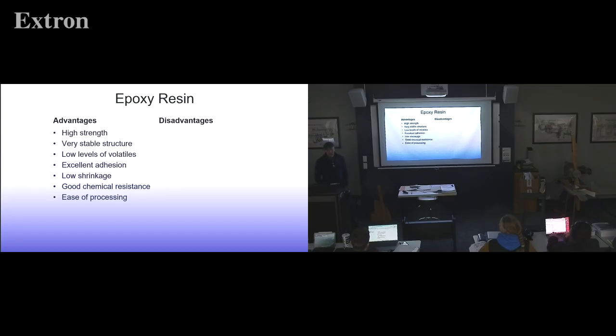And I kinda like the West System, but if you gave me a choice to use the other epoxy that I like, an MGS resin, I would pick the MGS every time. I just like the longer working time that I get from the MGS because I can add slow hardener or fast hardener, or I can mix a combination of those two to get a certain amount of time. If you use slow hardener with MGS, tomorrow morning after you get back here, it's not gonna be hard yet. Whereas this West System stuff, you lay it up in the morning, you might even be able to start grinding on it later in the afternoon. You know, but grinding on resin that's not fully cured, not a good idea.